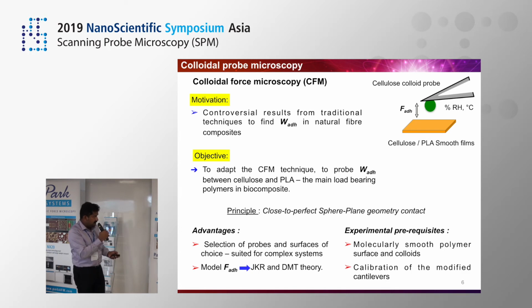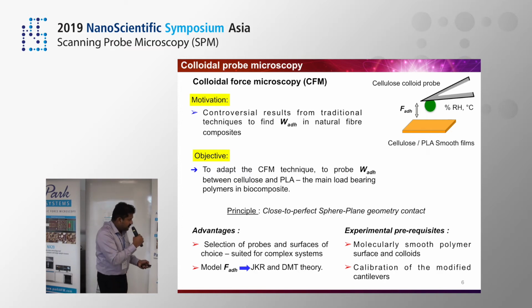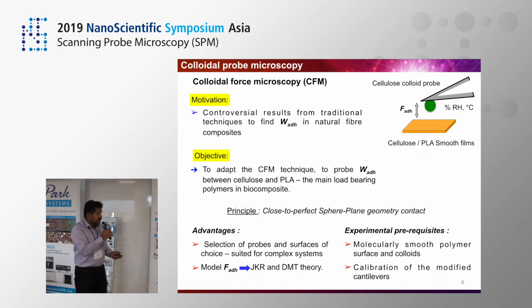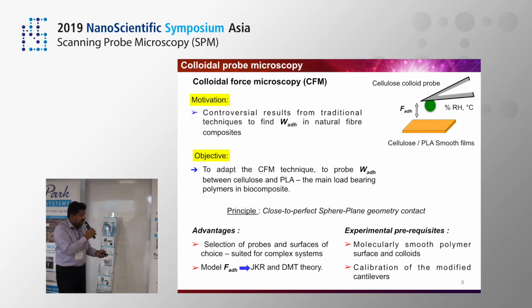So the CFM, the colloid probe technique, allows selection of probes and surfaces of choice to study complex systems, and the force of adhesion can be modeled using contact mechanics theory like JKR, Johnson-Kendall-Roberts, or Derjaguin-Muller-Toporov theory, depending on the case. And as I told before, the experimental prerequisite is smooth polymer surface and colloids, and calibration of the cantilevers after we stick the beads.